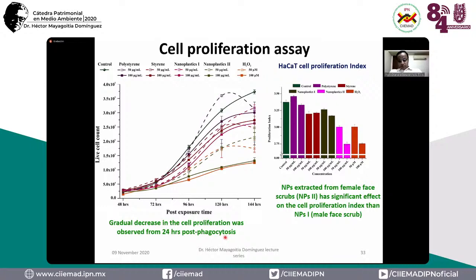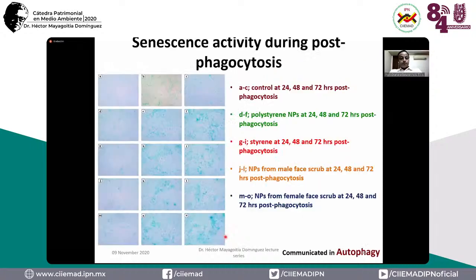And this paper is now in review in the journal Autophagy. And this is the senescence. We could see the aging of the cell due to the nanopolystyrene, senescence activity during post-phagocytosis. After 72 hours post-phagocytosis, the cells started to die off. That means slowly they started to age. We could identify the cell aging.